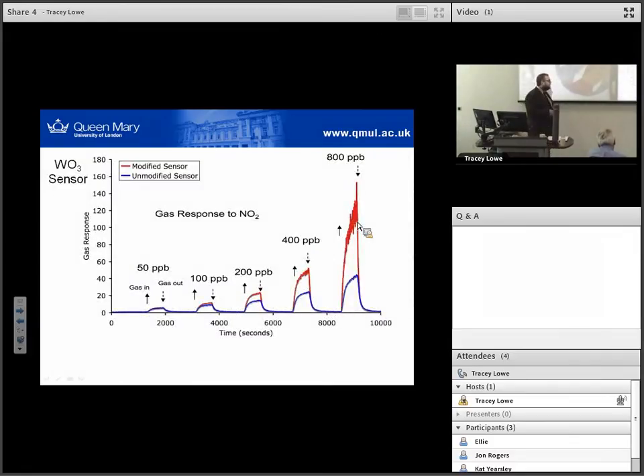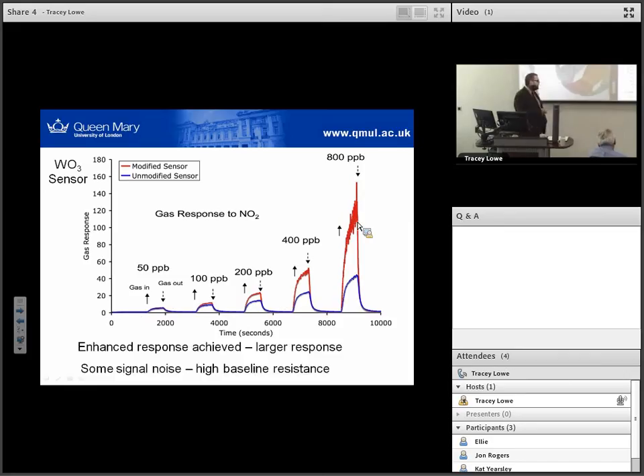We see a similar kind of thing this time with nitrogen dioxide, a different sort - it's an oxidizing gas. One of the problems with producing nanomaterials, as I mentioned, is you produce a lot more grain boundaries, and we see quite a lot of noise in our signal. Although these are very, very good responses at these part per billion levels of this gas, so we were very pleased to see this.